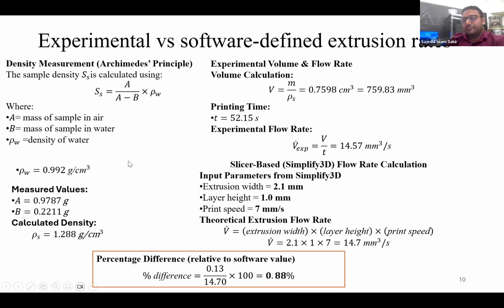What I have done is print something like only one layer, two layers, six layers, very small pieces, for measuring this density in the device we have in our lab. Then I measure the volume of it. And when I'm printing it in the printer, I take the time calculation, like the printing time.